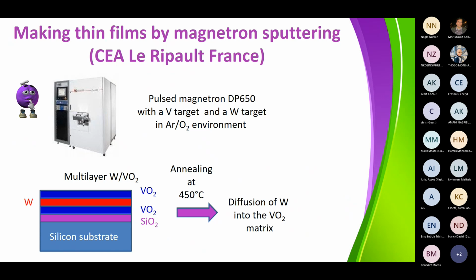Okay, and the films we are not making them in Le Mans. They were made at the Commissariat à l'Énergie Atomique, CEA, Le Ripault, France, by pulsed magnetron deposition. And they were using a vanadium target and a tungsten target, and working in an argon-oxygen atmosphere, so that they were able to produce some films.